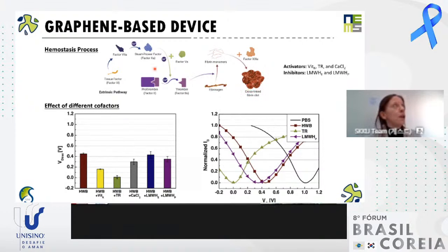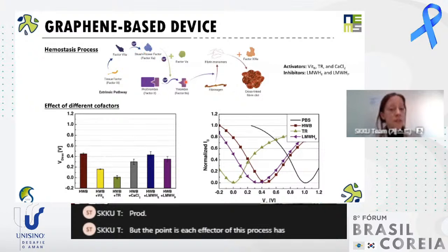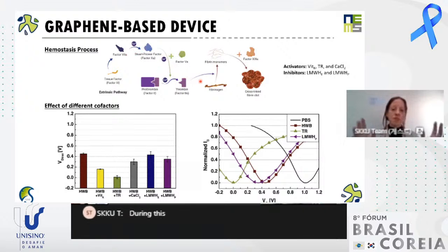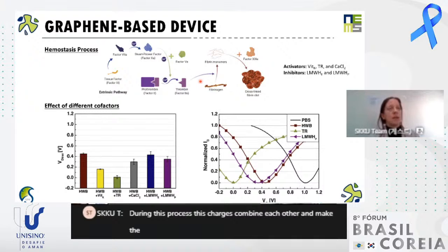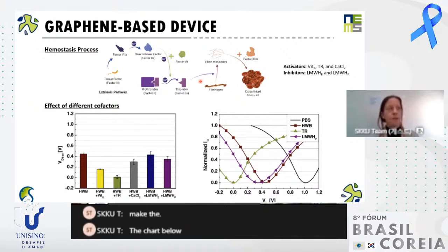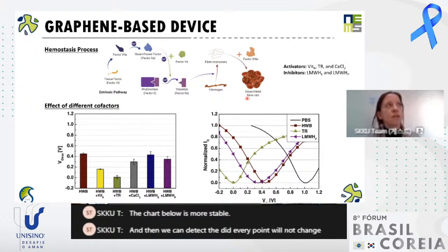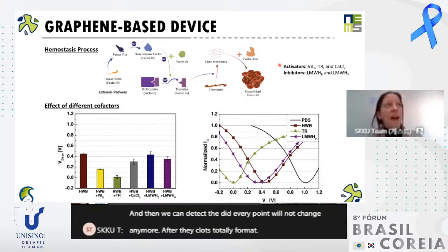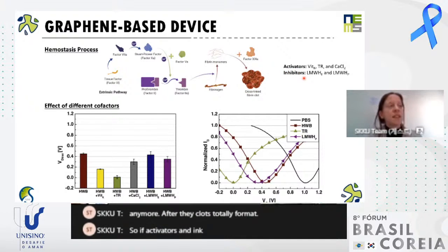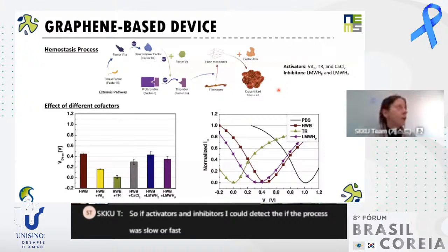But the point is, each factor of this process has a negative or positive charge. And during this process, these charges combine with each other and make the charge balance more stable. And then we can detect the Dirac point will not change anymore after the clot is totally formed. So with activators and inhibitors, I could detect if the process was slower or faster than normal.